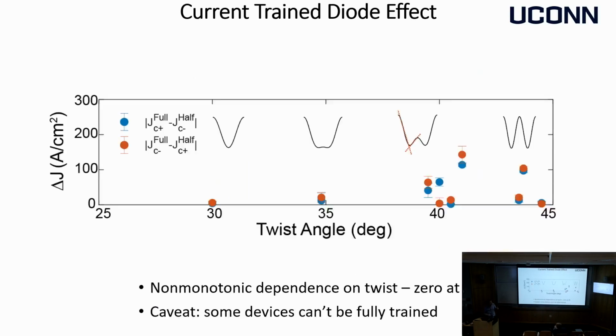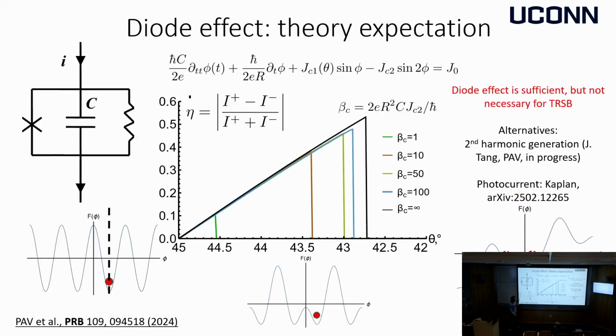Okay, so this effect has been proved in a multitude of samples having different twist angles and so on, and what you can see is that the efficiency, this is the diode effect efficiency, actually goes down at 45 degrees, where I just tried to convince you that time reversal symmetry breaking is the strongest, then it goes up, and then finally it goes down when you go far away from 45 degrees. Turns out that if you do actual calculations, without going into details, we just model the junction in the well-known RCSJ model, in which you have a Josephson junction, but in parallel you have quasiparticle resistance and some capacitance of the junction because it's like a parallel plate geometry.